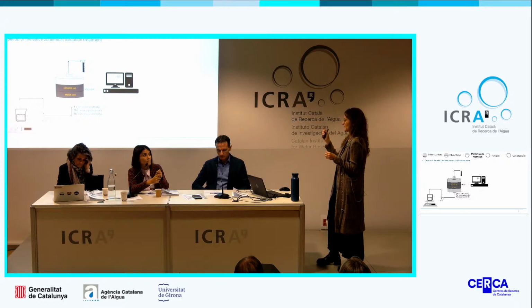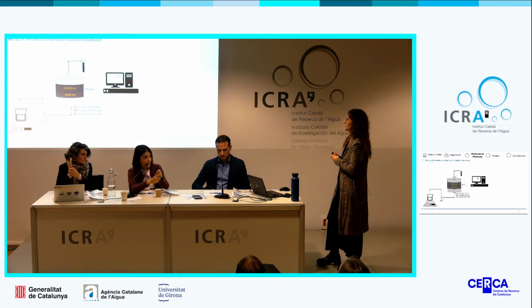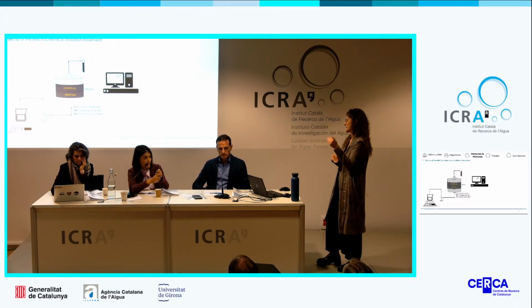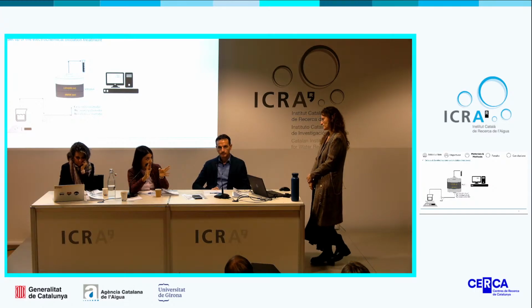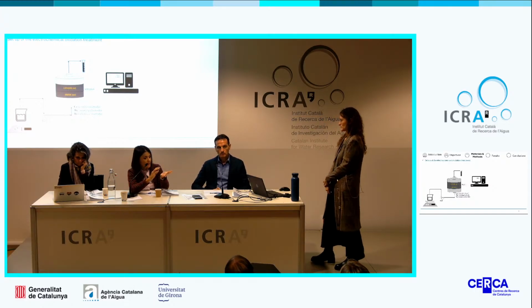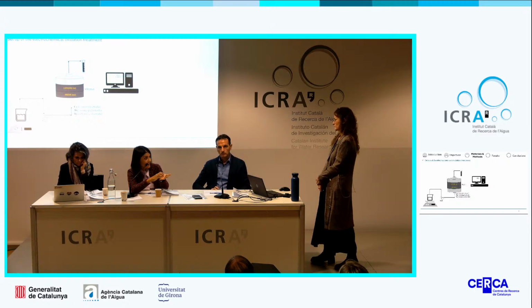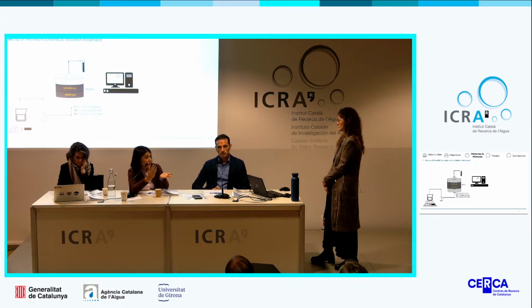But we usually take the sample during the open circuit conditions, and we use liquid chromatography and mass spectroscopy to quantify the percentage of removal during the open circuit condition, normalizing this to the initial condition. Yes, but at the end of the treatment, if you measure the type and the concentration of the pollutant retained in the electrode, you will be able to determine the main byproducts, maybe, or not.